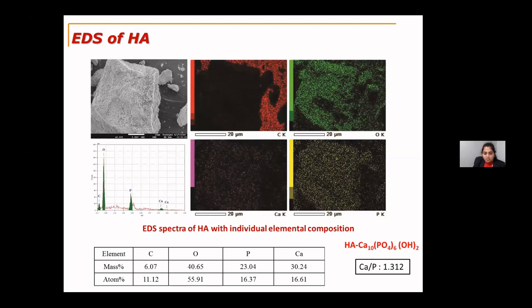Also, the mass percent and atom percent were recorded here. So the calcium by phosphorus ratio is 1.312. For the commercial hydroxyapatite which we obtain, the calcium to phosphorus ratio is 1.56 to 1.6. So the calcium to phosphorus ratio is 1.3 for the bio-based hydroxyapatite, which is not bad, and this can definitely be used for biomedical applications.